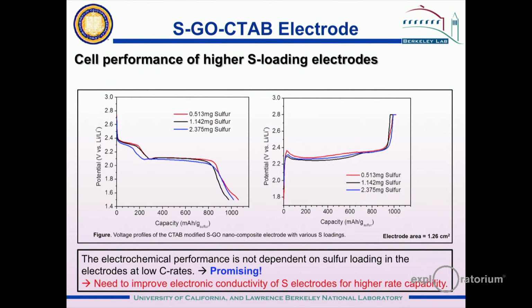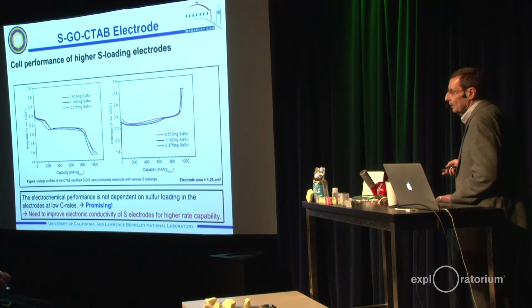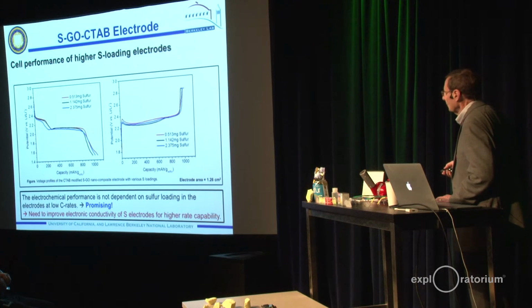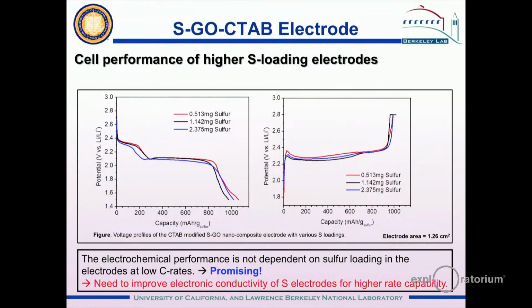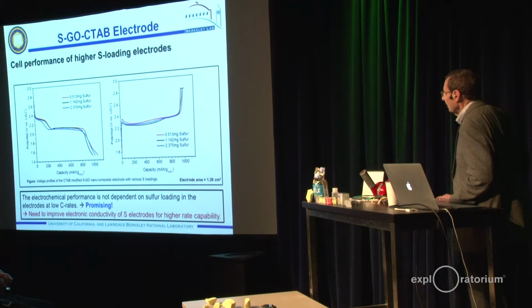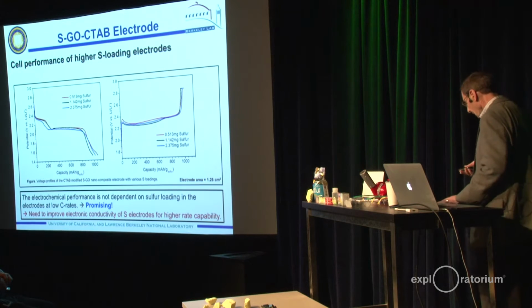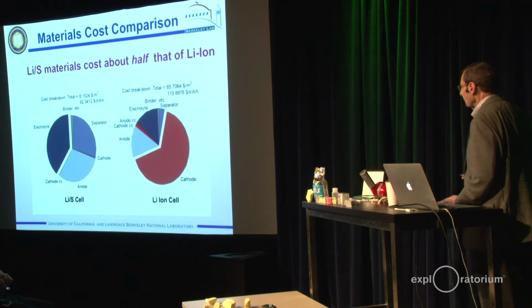So the next thing we needed to do in order to have a cell that is commercially interesting is to increase the amount of sulfur in the sulfur electrode. These experiments show that as we go up from 0.5 milligram of sulfur per square centimeter to about 2.5 milligrams of sulfur, we get essentially the same utilization of the sulfur. So that's very good news. And these are the discharge curves and these are the charge curves. So that means that the scale up in the loading of the sulfur is very promising for potential commercialization.